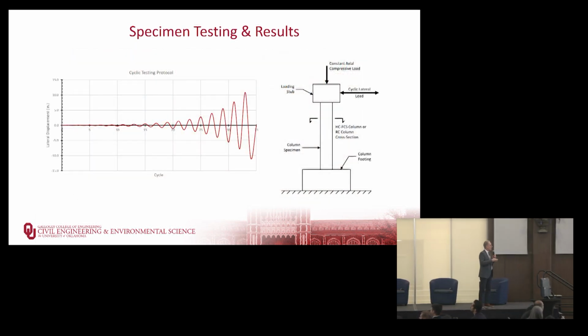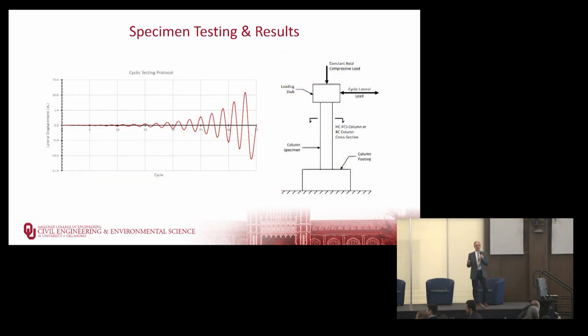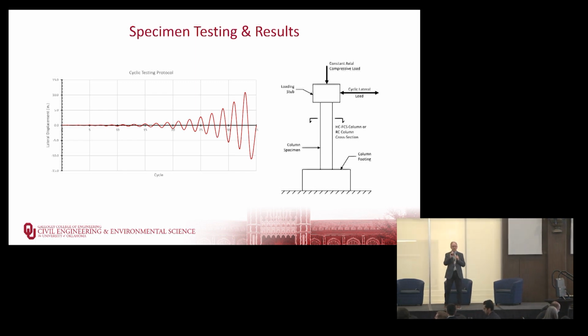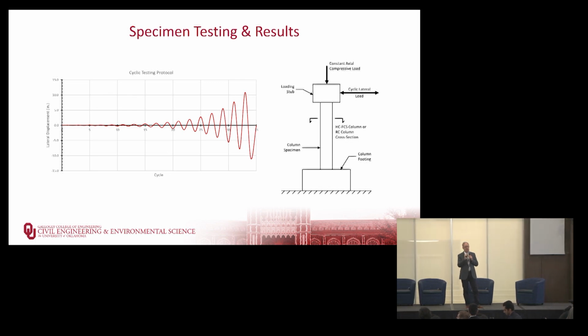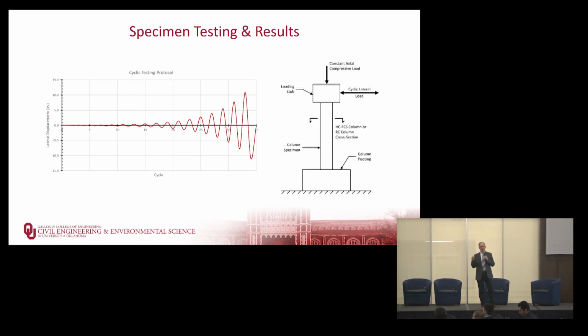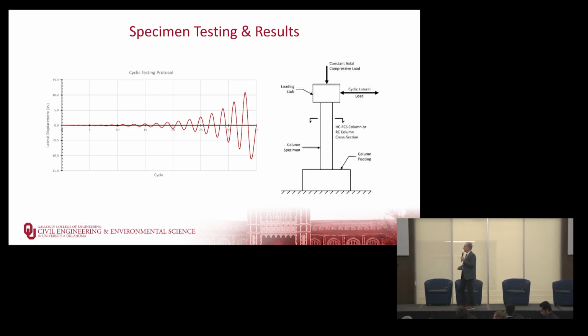The loading protocol is based on a typical loading protocol for cyclic loading of columns. It's a FEMA guide where you start out with a small push and pull displacement-wise, and then each subsequent cycle you increase by 40%, and you do 2 cycles at each displacement. So this is a displacement-controlled test as opposed to a load-controlled test.